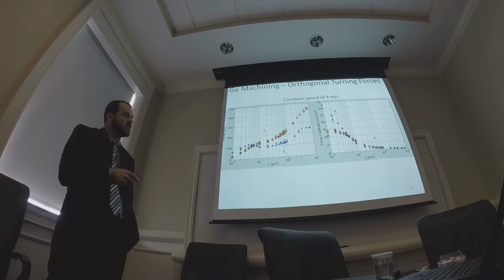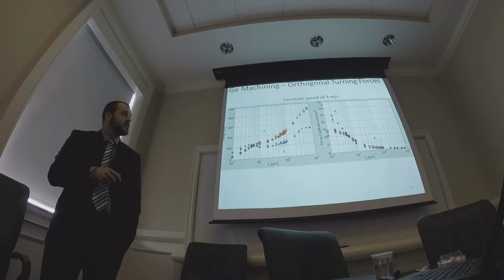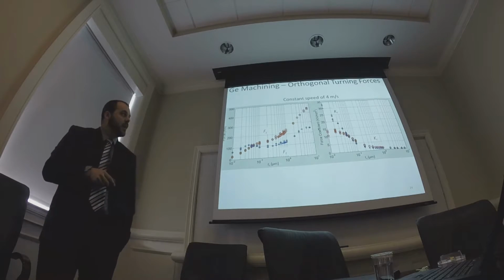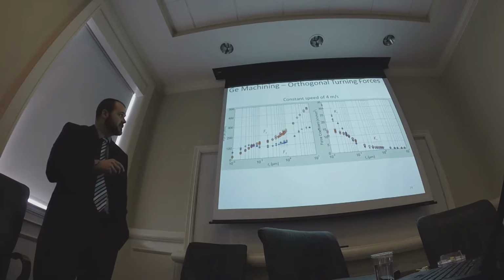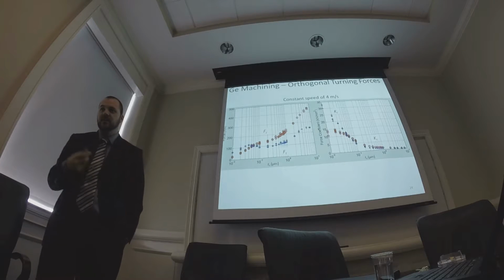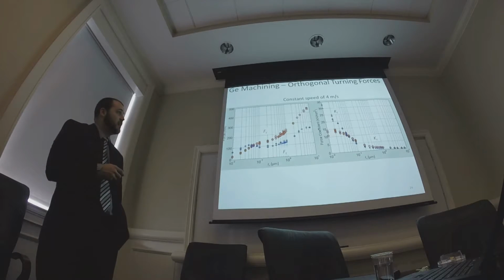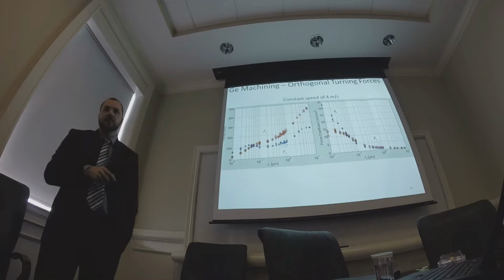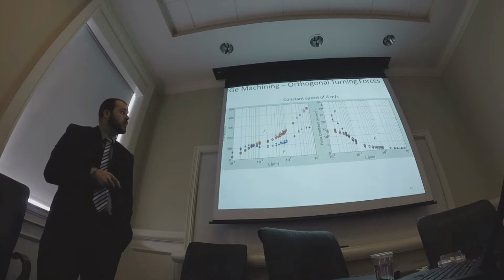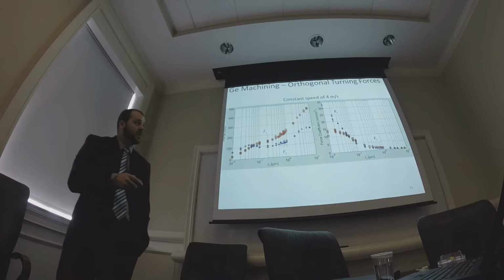But then the cutting force coefficient doesn't continue increasing, it sort of levels off in this range. On the log scale it looks flat all the time, but in the ruling or planing we never drop below about 5,000. The force coefficient never dropped really below 5,000.